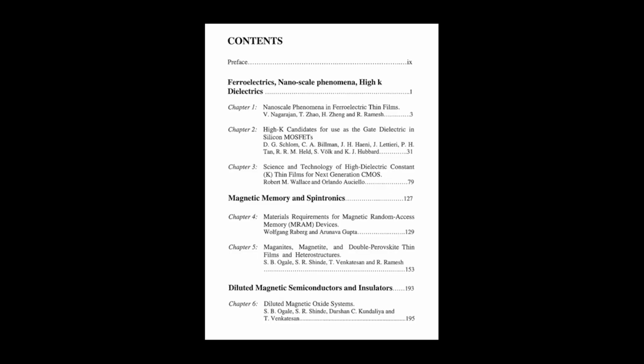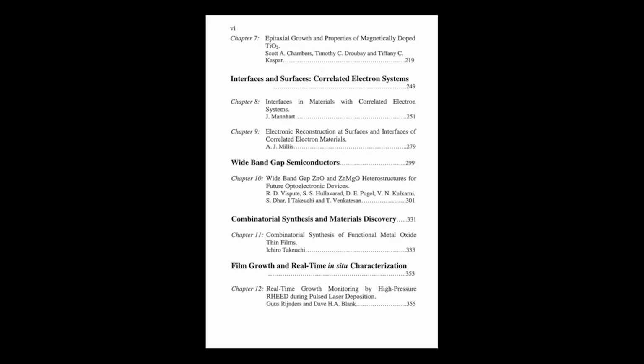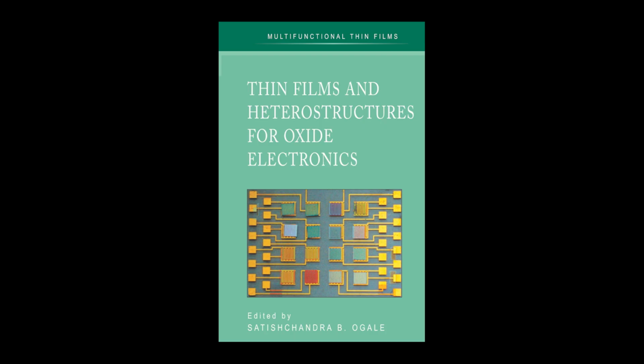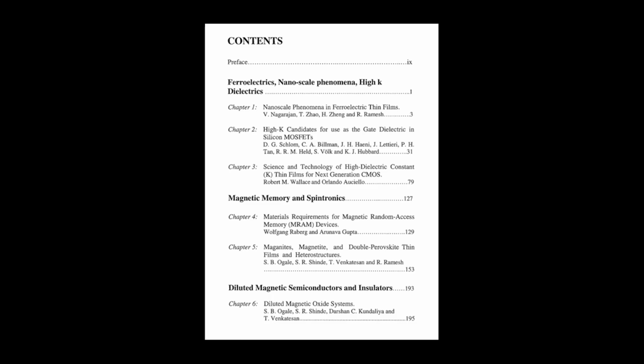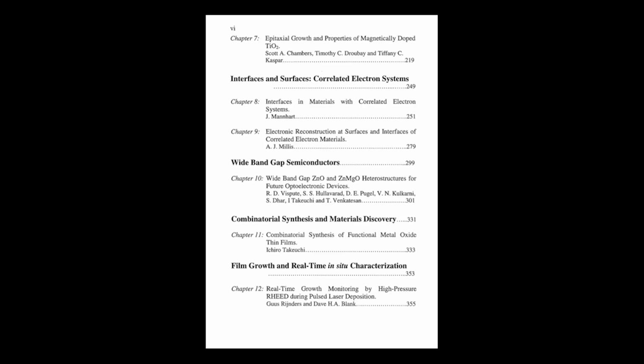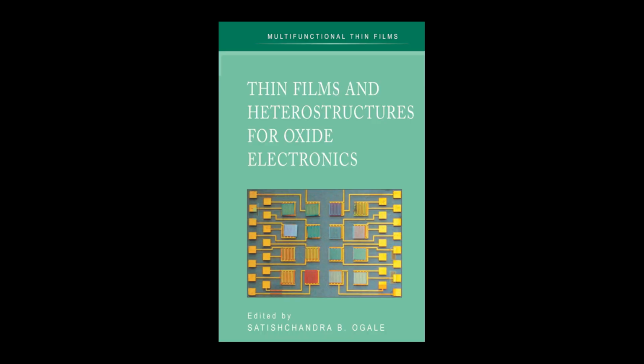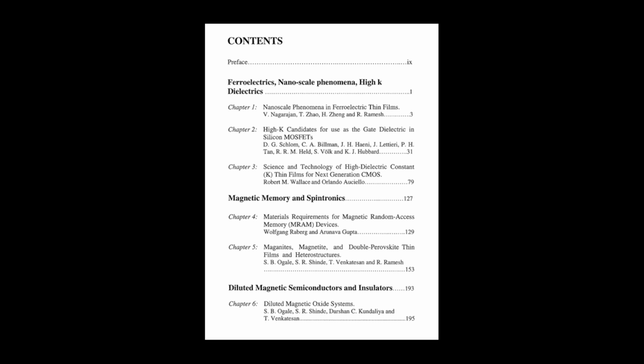Exactly. PLD uses intentionally short, fast laser pulses to deposit maybe just a fraction of a monolayer, followed by a relatively long interval, maybe half a second or so, with no deposition. This pause gives the atoms the time they need to fully reorganize and recrystallize, forcing the growth into a layer-by-layer mode, even under conditions where it would normally roughen up. You're using a high-tech pause button, timed perfectly using RHEED to maintain atomic smoothness. That's the essence of it. It allows for incredible control over interface quality, which, as we've seen over and over, is paramount for almost all these advanced oxide devices: ferroelectrics, MTJs, correlated heterostructures.